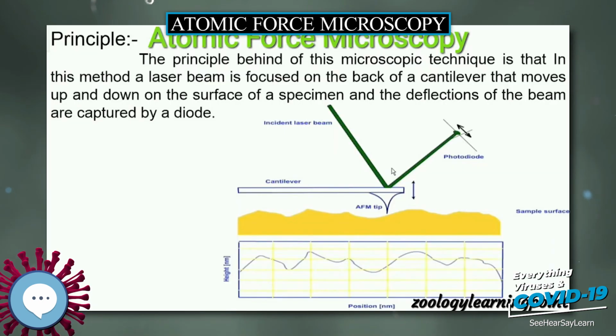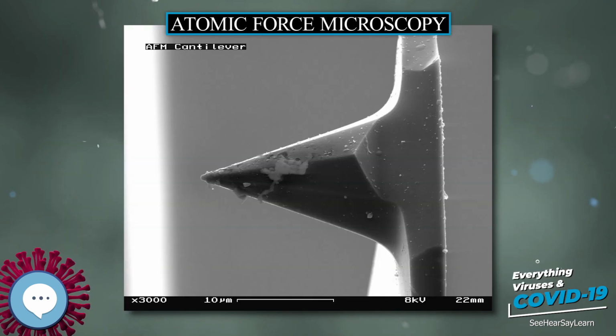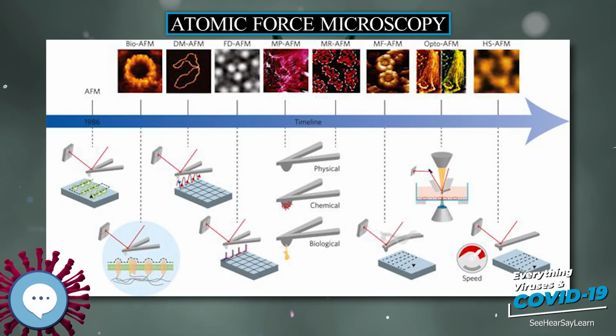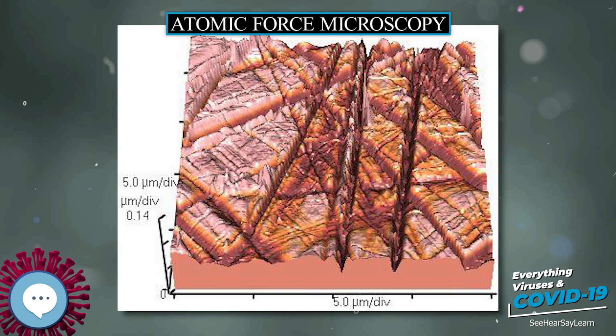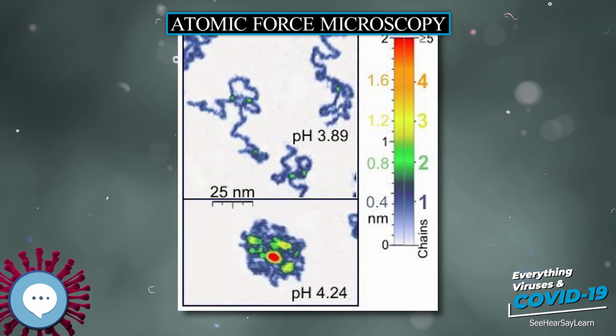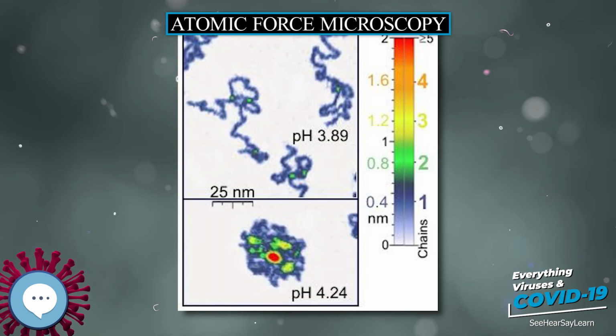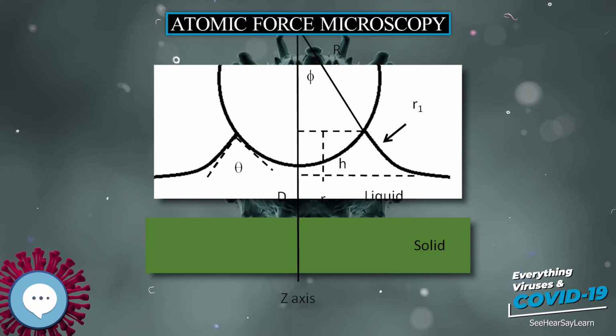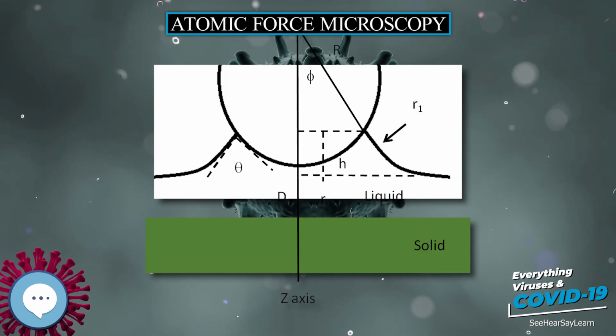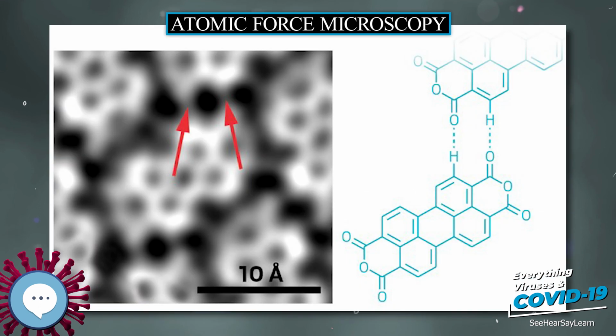Furthermore, AFM was used to measure, in an aqueous environment, the dispersion force due to polymer adsorbed on the substrate. Forces of the order of a few piconewtons can now be routinely measured with a vertical distance resolution of better than 0.1 nanometers. Force spectroscopy can be performed with either static or dynamic modes. In dynamic modes, information about the cantilever vibration is monitored in addition to the static deflection. Problems with the technique include no direct measurement of the tip-sample separation and the common need for low stiffness cantilevers, which tend to snap to the surface.